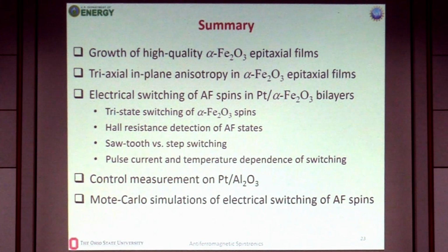I think that's something we didn't discuss so far. Iron oxide, you mean? Yeah. In general, 30 nanometer is quite a thick film. So if you calculate the efficiency, it would have to be rather gigantic. So here's the interesting thing that we didn't put in the paper or I didn't talk about. This thing has a pretty weak thickness dependence. So we did something like 20 nanometer, 50 nanometer, 60 nanometer. The amount of current needed is more or less the same, considering the sample fluctuation.